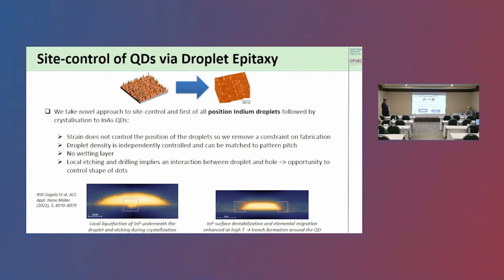And you can see here, from the previous slide, that we've observed etching in the dots forming in the pits. These are some very nice images from Paul's group that show that under different growth conditions, we have our quantum dots, and you can get some local drilling underneath, but you can also get these dots appearing in etched pits.